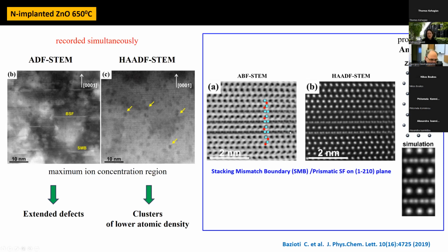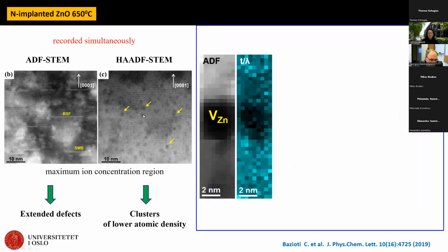We characterized many different stacking faults. So this was a prismatic stacking fault of Amelinckx type. I will not insist on all the structural work that we did, but I will focus more on the spectroscopy side. And the main question here, as I said before, was to understand what happens with nitrogen. And since nitrogen is a very light element, EELS spectroscopy, in contrast to EDX, is the appropriate one for this detection. So working along these nano-sized clusters, you can see at first place an intensity ADF map and the